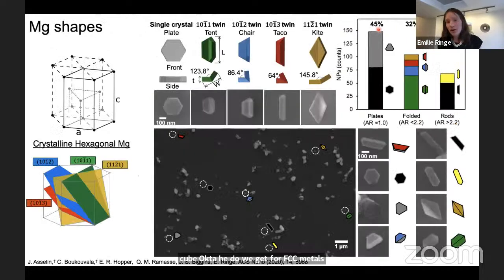And lo and behold, experimentally, this is what we get, right? So we see the tents, the chairs, the tacos, and the kites in our reaction mixture, and their proportion within the reaction mixture for the twin structures is actually related to the energy of these twin planes.